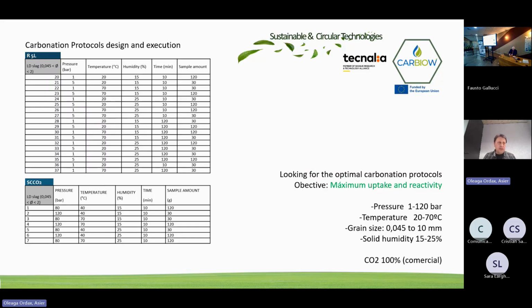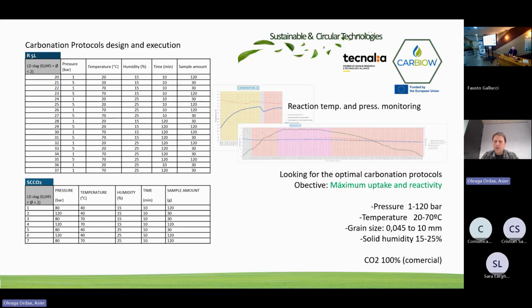because we couldn't have availability of the CO2 coming from the carbon in this project, because it's very complex, very costly, and not enough volume. So Carbiow project CO2 is going to be nearly as pure as the CO2 we use, so it's comparable. Mineralization can work with very poor CO2 fluxes also, like a flue gas of chimney, but obviously the effectivity is bigger with the pure CO2. We try to control with the classic approach of temperature and pressure monitoring the reactor.